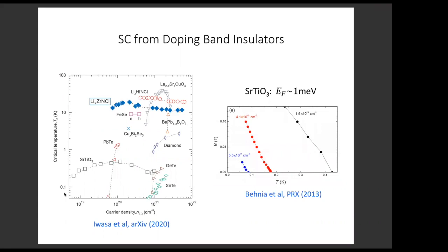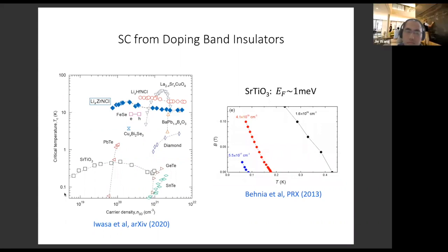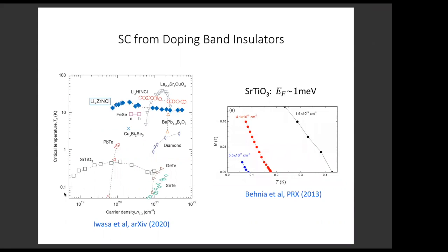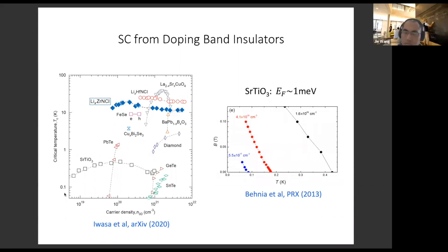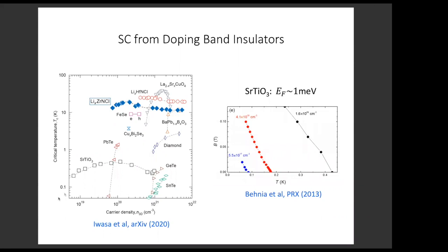And it's remarkable that, for Fermi energy as small as 1 milli-electron volt, superconductivity still appears. And there are many other materials: germanium telluride, tin telluride, lead telluride. These are all semiconductors, and upon doping, they give rise to superconductivity. Another material is copper-doped bismuth selenide, something I thought a lot about. So then the question is, can the mechanism that I described account for superconductivity in those?